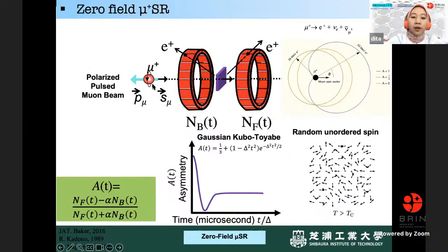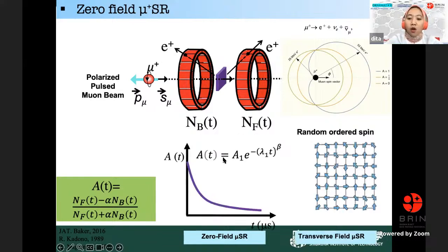Okay. So if we have the polarized muon beam, then we hit the muon beam into our sample. So we will have asymmetry with polarization. We will have muons that are scattered, not in 100% one direction. And then we can count the asymmetry of the positron, which is the decay product of the muon, in the forward and backward counters. So we count how many positrons in the backward and the forward. If we have a system with unordered spin, usually at high temperature, we will see this typical asymmetry curve, the so-called Gaussian Kubo-Toyabe. Or if we have spin, but it's random, we will see an exponential term. So we will see a decay like that in the muon spectra.